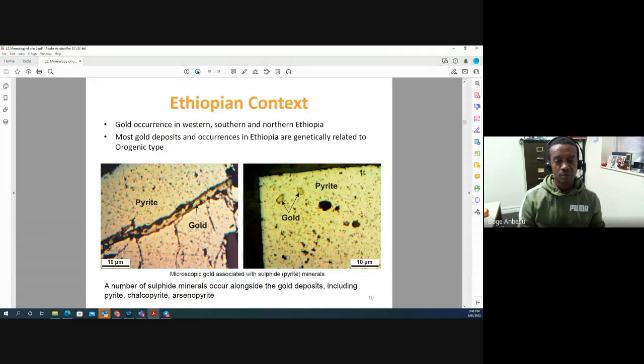In this case, for example, the primary mineralogy for this type of ore body is pyrite hosting the gold. Depending on what you look at, gold can be coarse grained in pyrite, which essentially makes it easier to process, or the gold can be microscopic. So very finely disseminated gold all over the sulfide mineral, which means that you have to first separate out the sulfide, in this case pyrite, and then do some kind of pretreatment before leaching it directly.